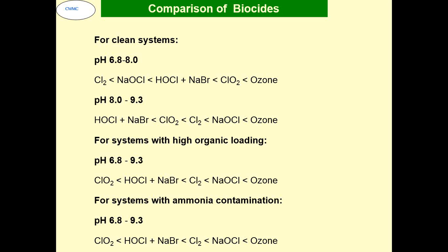Now, if we compare the different oxidizing biocides, for a clean system with a pH of 6.8 to 8, chlorine is the cheapest one, followed by sodium hypochlorite, and the costliest is ozone. At pH 8 to 9.3, hypochlorite plus sodium bromide are supposed to be cheaper. Chlorine dioxide is a good choice there. Ozone again is the costliest one.